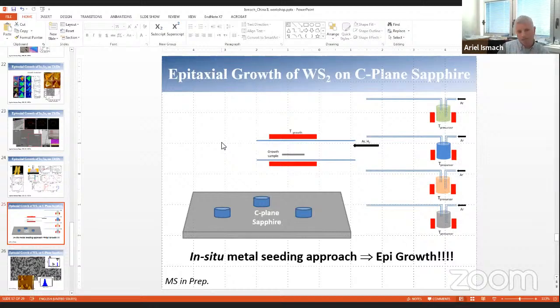We invested a lot of effort in trying to understand what the key parameters are here, and we couldn't find the answer. And finally, after several months of hard work, my PhD student found out that when you do, prior to the growth, an in situ metal seeding approach, so you basically expose the substrate only to the metal precursor, thereby creating nanoparticles of this metal on top of the sapphire, we increased the chances to get epitaxial growth from about 10% to more than 95%. So that means that this seeding approach is significant for this epitaxial growth.